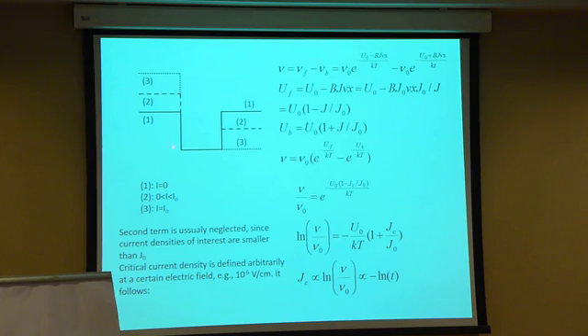So what happens in case 1? This is the potential well in the absence of any currents, absence of Lorentz force. So the flux bundle tends to jump this way and this way. The probability of jumping in either direction is equal, so you will have a total net movement of zero of vortices in one direction or another. Now, if you apply a current, you will deform the potential well in such a way that in this direction it will be more difficult for the flux bundle to jump, while in this direction it will be much easier. And this is the characteristic law of the probability of jump. At a certain value of current, in one direction the potential well goes to zero, and it is very easy for vortices to move in this direction.